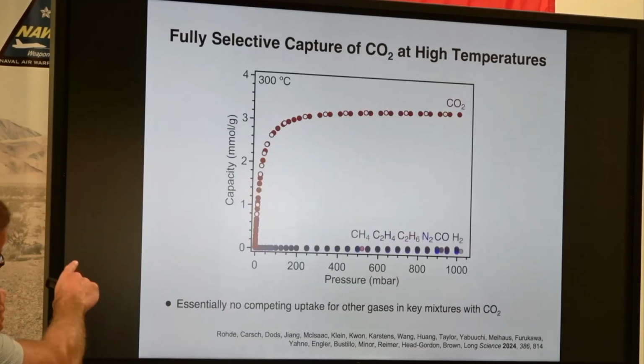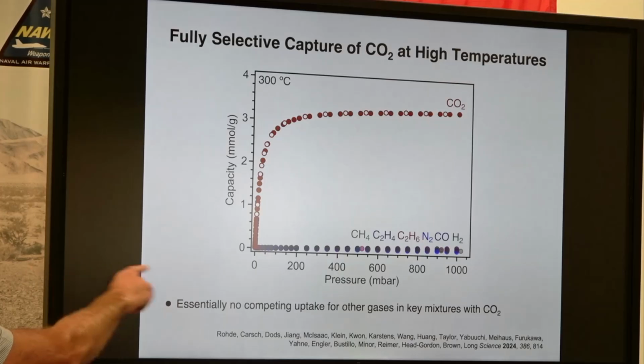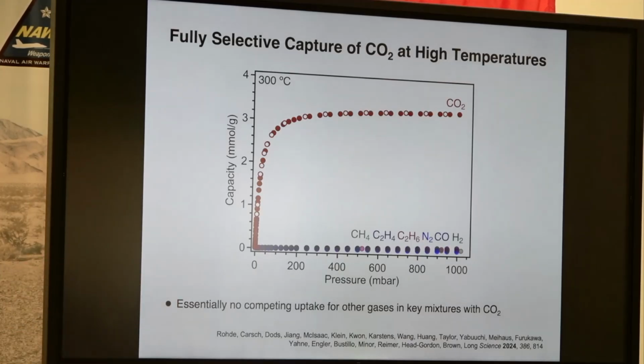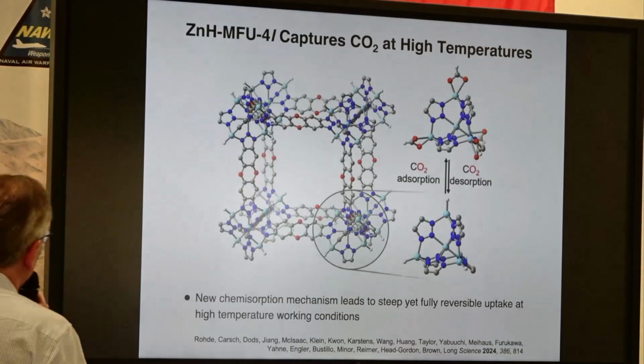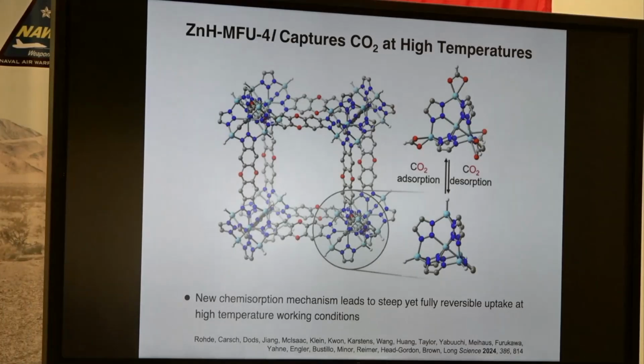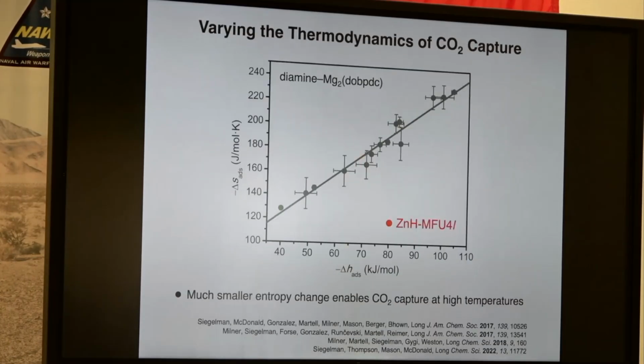So normally CO2 in a solid, like physisorption, it's going to be like the other gases at the very bottom. There's no uptake. At 300 degrees C, you have a huge entropy penalty. The heat means the molecules want to be in the gas phase. And what's happening is at high temperature, we're overcoming a reaction barrier and we're making the formate. And the thermodynamics are such that it wants to bind at 300 degrees C. And part of that is the entropy.